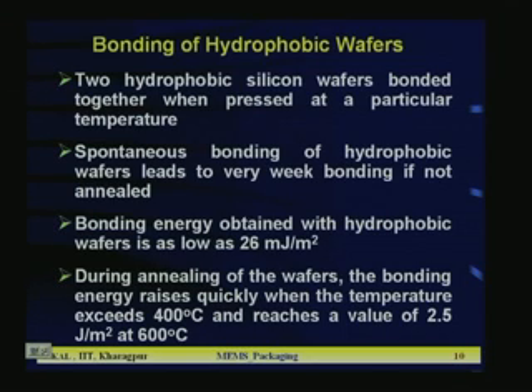Now, in case of the hydrophobic wafer bonding, the bonding energy is nearly 26 millijoule per meter square, that is the bonding force or bonding energy. Now, it has been observed that if you go on increasing the hydrophobic bonding temperature, the bonding strength also increases. For example, if you increase the temperature from 400 degrees C to 600 degrees C, the bonding energy will increase from 26 millijoule per meter square to 2.5 joule per meter square.